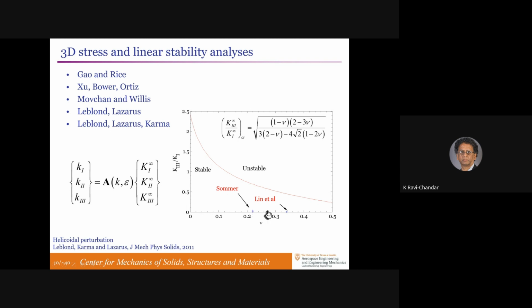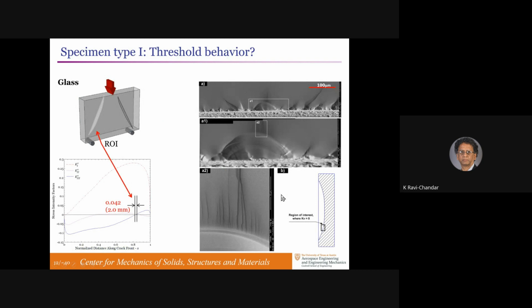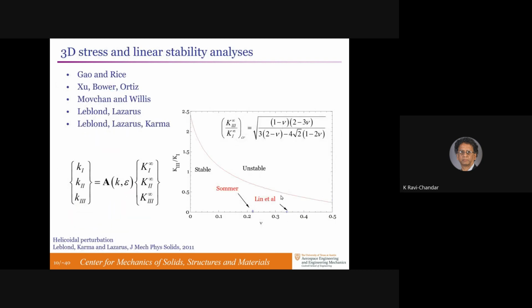We did some experiments about 15 years ago and found that the instability set in with a different material, different Poisson's ratio, essentially when K3 was negligibly small. So something is not right about this criterion. So we need a new criterion. So we took a leap of faith. I'll come to the leap of faith in a little bit.